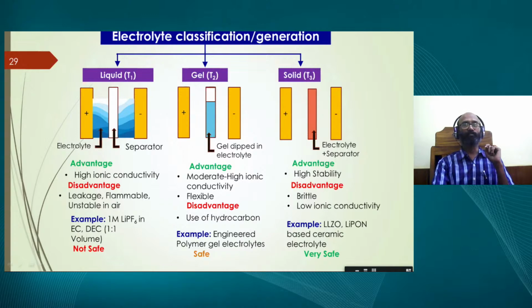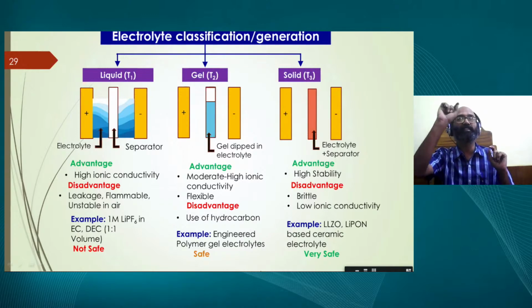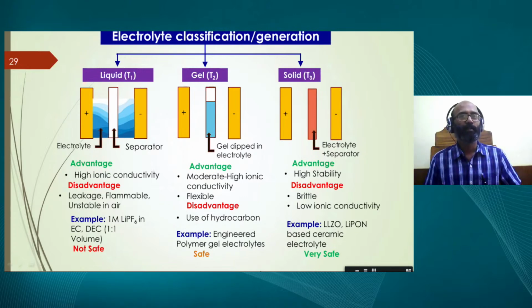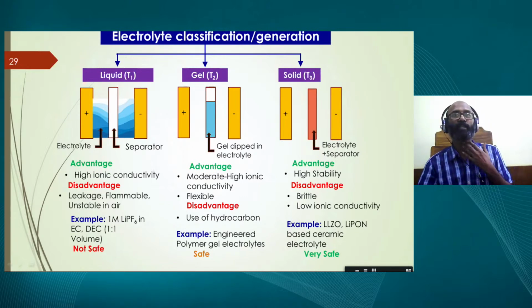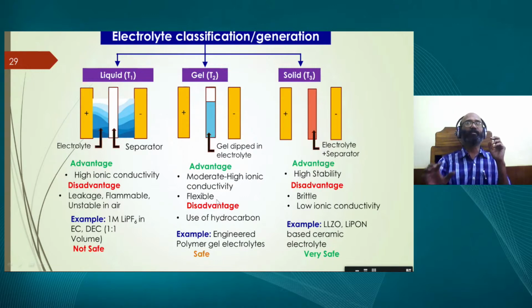And if you go for the gel batteries, if they are written as lithium polymer batteries, they are better. They are reasonably safe because you don't pour the liquid there, rather you only have a gel, with a very small amount of liquid. In some cases you still have some carbonate which is going to decompose at 70 degrees. At high temperature it's not good, but at room temperature they are very safe. They have moderate conductivity, and the only thing is you need to engineer the polymer gels for safer activity. So you need to play with that. There is a lot of research in it, and people have done a good amount of research.